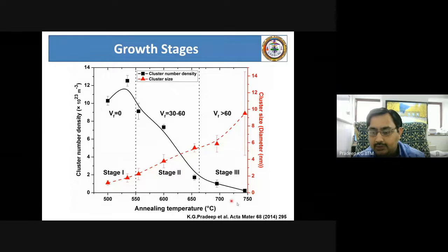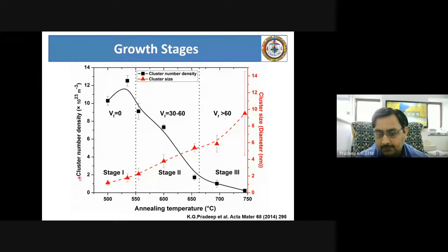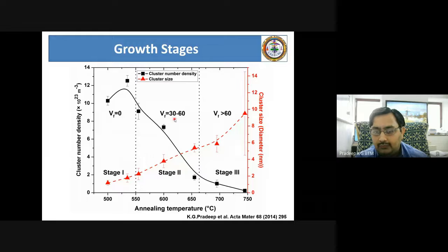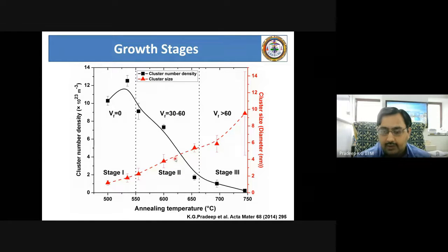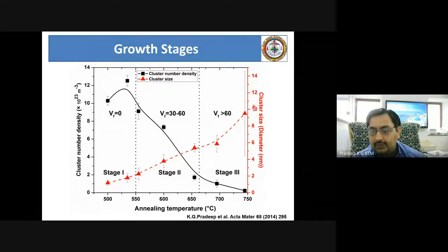Now, based on this difference, you can categorize this evolution into 3 different stages. Stage 1, where you have the emergence of the clusters with the highest number density but the smallest size. And stage 2, we have a reasonable volume fraction of clusters but with coarsened nanoscale features. And stage 3 is the almost negligible number density but very few larger size precipitates that have emerged.